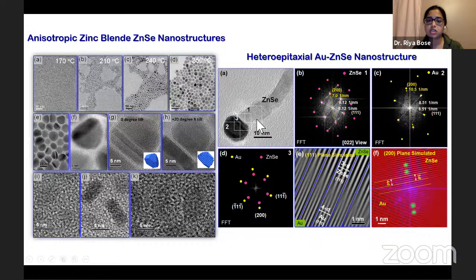Now you can see that this image actually shows two different contrasts. So one part is darker and one part is lighter. So as I have said already, TEM collects electrons that are transmitted through your sample. So if you have two materials with different atomic numbers, the one with the higher atomic number will let fewer electrons pass through it. So you can think of it as something thick, and light cannot pass through it properly. So the electron beam also cannot pass through that sample with higher atomic number properly, and it casts a darker shadow. So you can see the gold creates a darker contrast, and zinc selenide is of lighter contrast. So we can clearly distinguish two different materials.